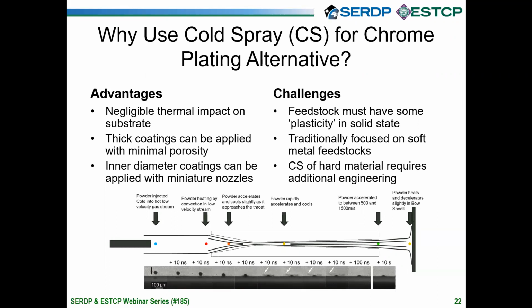Another advantage is that because we don't require a significant heat source, we can design nozzles that are small enough to fit inside inner diameters so that we can coat very long tubes on the inner diameter of the tube, and we can go down to about 2 inches inner diameter.